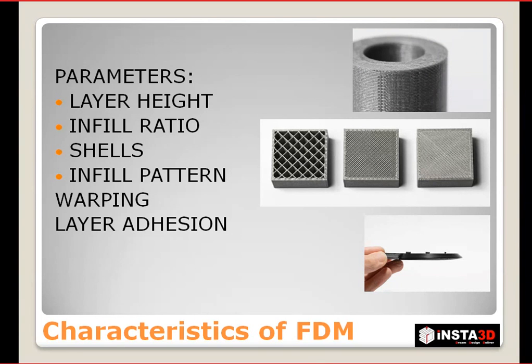Next we can see about the warping effect and layer adhesion of FDM 3D prints. The warping effect is an error caused in FDM 3D printers, and it is shown here in this image. You can see a 3D printed part which is slightly bent. This warping effect happens when, just imagine you are 3D printing in an FDM 3D printer, the first layer is formed and each point in the first layer cools at different cooling points. The first laid material will cool faster than the latest laid material, and these different cooling points make the second layer pull the first layer upwards. So you will get an internal stress inside the 3D printed part, which makes the product warp, as shown here in the image.